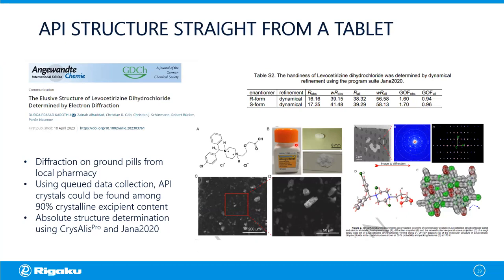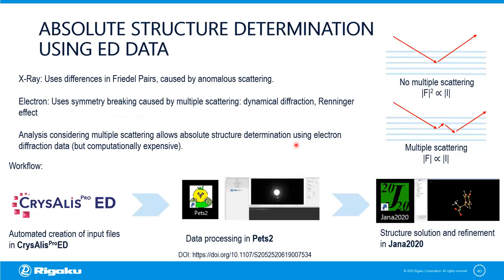And this provides a nice segue into the next discussion. I mentioned very early on that one of the features of electron diffraction is that we have to deal with dynamical scattering. That means that we have multiple scattering events, and this changes the intensity of the resulting diffracted beam in a way that can be calculated, and can correct for various effects within the crystal lattice.